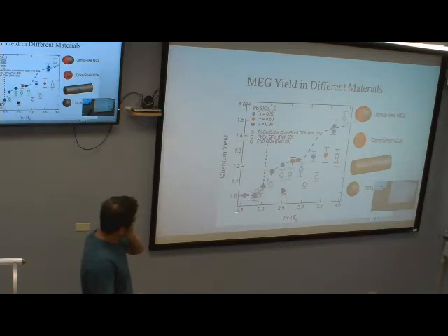So the excitation energy is the ratio between the photon energy and the band gap of the material. The efficiency starts to go above 1 when this energy goes above about 2, and then there's a plateau from 2 to 3, and then a huge increase after 3 times the band gap. So this line is closer to the result from the core shell one.